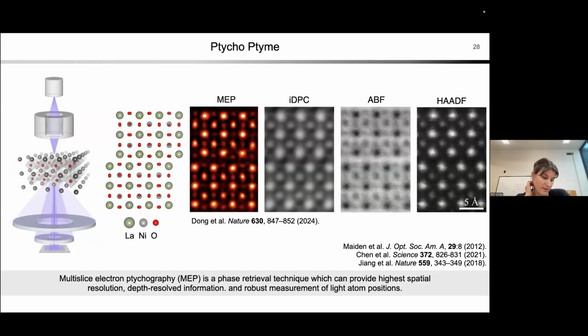Now, this is where we need to really turn to the most cutting edge electron microscopy. And so what we're particularly interested in, in these new nickelate superconductors, are actually the positions of the oxygen columns. And I'll tell you why in a minute. But many of you will know that imaging light elements with high resolution and high precision is very tricky in these crystalline materials. And so we're really lucky that this scientific question coincides with the launch and development of this multi-slice electron ptychography technique, which gives us access to very high resolution and high precision measurements, even of those oxygen columns.